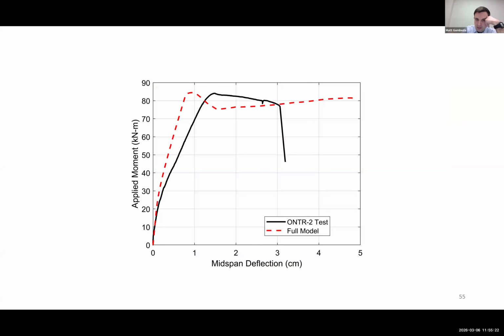And then here you can see the comparison of the test in the black curve with the full model that we had earlier, using the same computational modeling approach that we used earlier. And the peak strength is almost a perfect match. There's a little bit of a discrepancy in the post-peak behavior and the stiffness past the proportional limit, but in general, from a strength perspective, we were quite pleased with the comparison with the results.